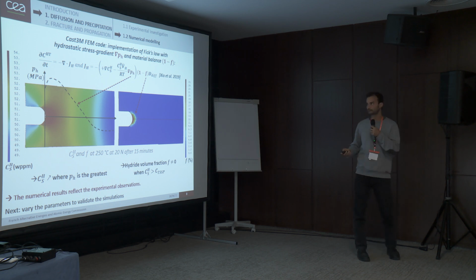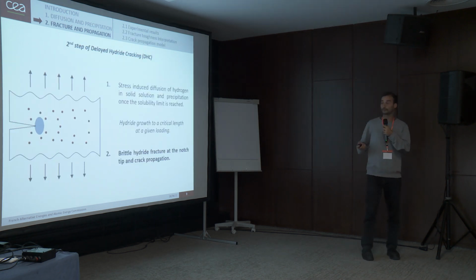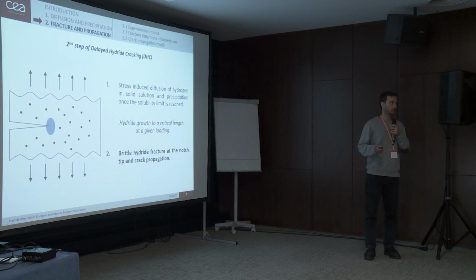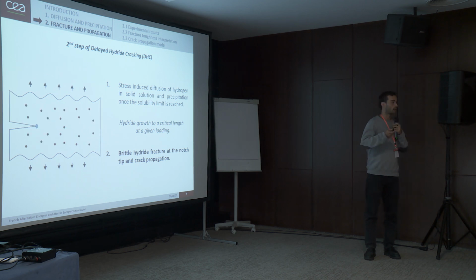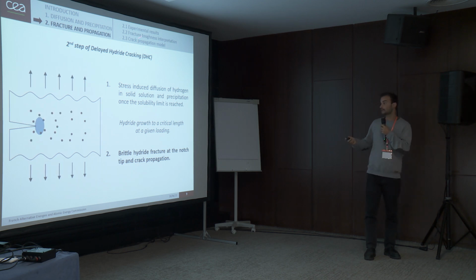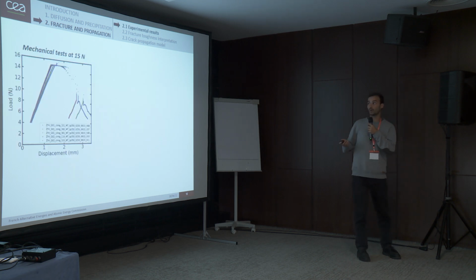the simulations. So we have seen the first step of DHC, which is the stress-induced diffusion of hydrogen in solution and the precipitation. And after that, there is the hydride growth to a critical length, and then there is the hydride fracture and the crack propagation. So now we are going to see this second step. So now we can take a look at the tests realized at 15 Newton.